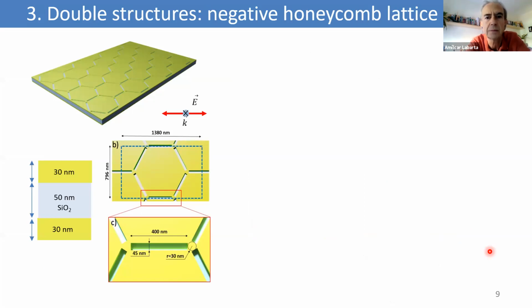Now the metal insulator metal stacking is a bit different because we have substituted the continuous wall mirror by an active plasmonic layer. So here we have something like a sandwich where there are two replicas of the same active plasmonic layer, which are facing each other, and they are separated by an insulator with a certain thickness. So this is a kind of plasmonic sandwich. In this case, the active layer is just the negative version of the honeycomb lattice of bars that I have shown previously. So to manufacture this sample, we carve trenches on a continuous gold layer. These kinds of systems could be useful when you need high reflectivity and low transmission.